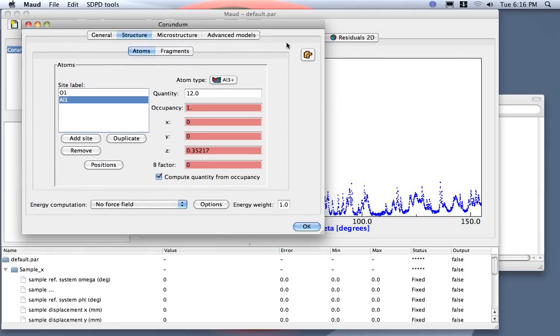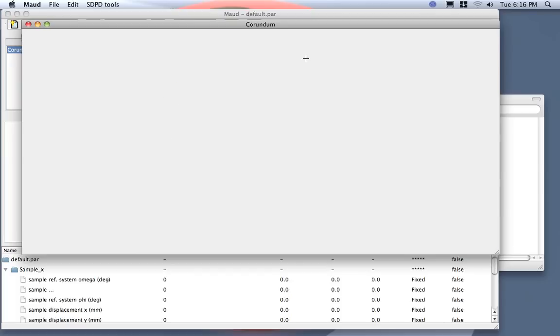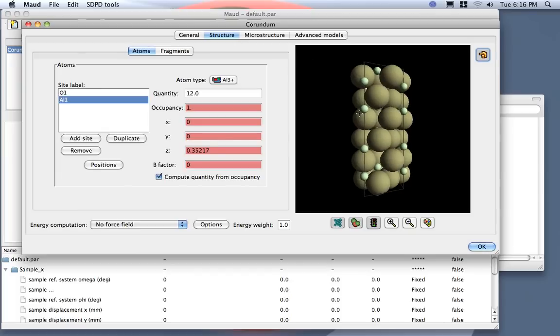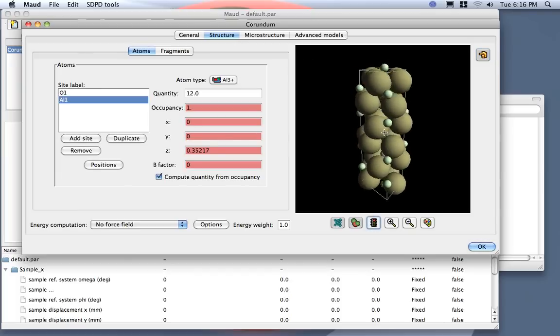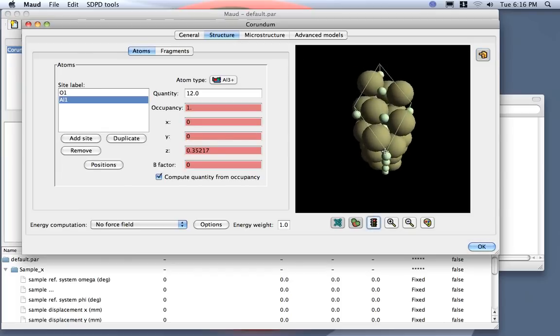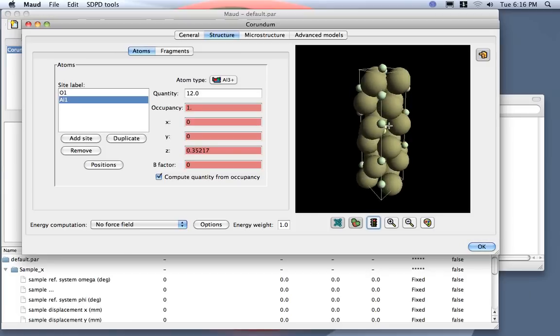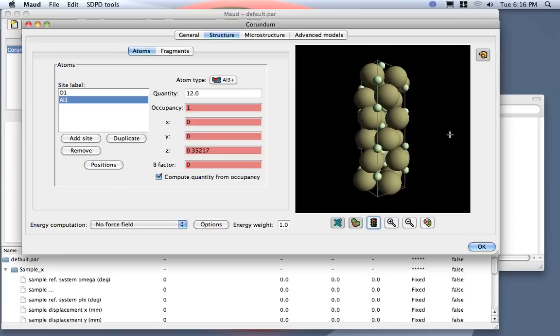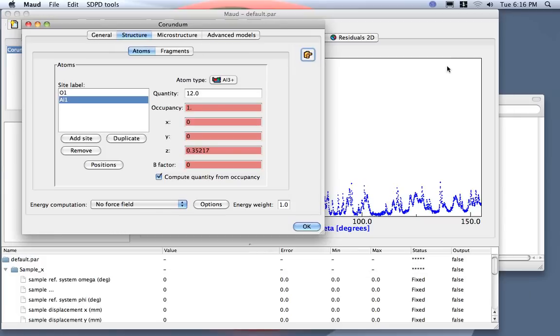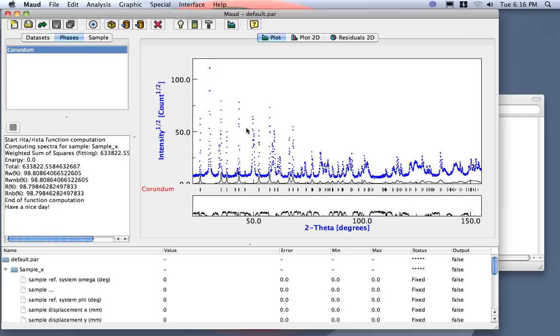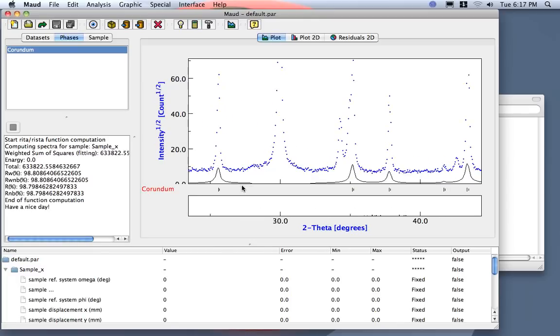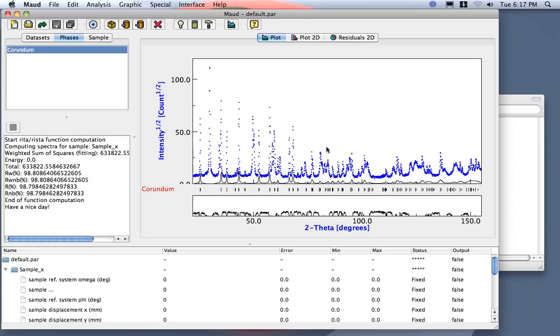You can also get a 3D plot here to see if the structure is correct. While I stop and drag manually, yes, this corresponds to the atom. Okay, let's say this is correct. I can compute and see where this corundum is going. Seems like it's actually taking this peak, this peak here, here, here, also the small one here. Seems like the corundum is a good one.